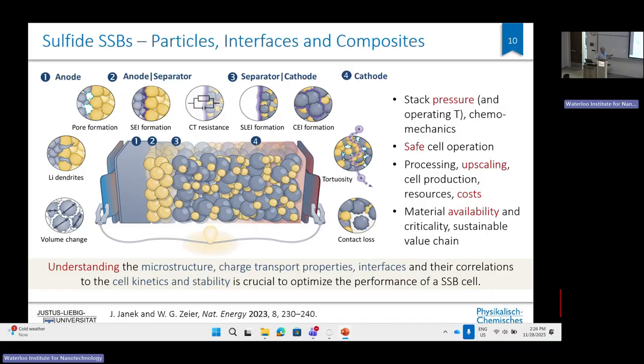And there are quite some issues, all related with the different interfaces in these cells. And what my group is doing is trying to understand really the microstructure and its correlation with the interfaces to bring down stack pressure. Because if you ever experienced mixing dry peas and beans, you will know there is always empty space in between, and contact may depend, in fact, if the peas and beans are deformable, on pressure, and that is a key issue with solid state batteries. So far they mostly operate at relatively high stack pressure, and that has to be reduced. It is one of the major issues.